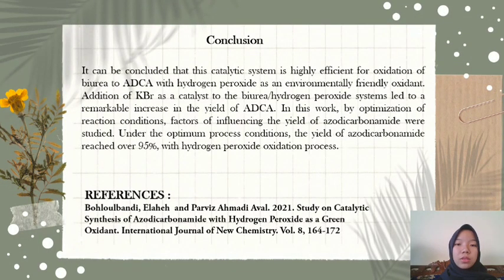The last is conclusion. It can be concluded that this catalyst system is highly efficient for oxidation of biurea to ADCA with hydrogen peroxide as an environmentally friendly oxidant. Addition of KBr as a catalyst to the biurea and hydrogen peroxide system led to a remarkable increase in the yield of ADCA. In this work, by optimization of reaction conditions, factors influencing the yield of azodicarbonamide were studied. Under the optimum process condition, the yield of azodicarbonamide reached over 95% with the hydrogen peroxide oxidation process.